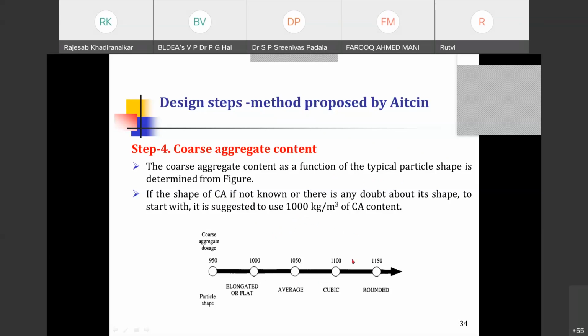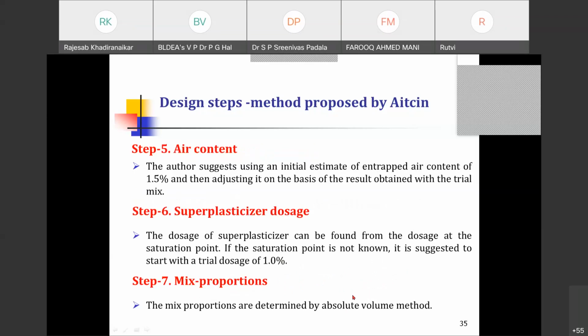If you have a clear-cut idea regarding the type of aggregate, then you can start with a range of 950 to 1150 for elongated and flaky. An average in this range, then for cubic shape you can go slightly higher, and for rounded still more. So based on the type of aggregate, you decide between 950 to 1150 kg per cubic meter. After that, the air content, and the authors normally suggest around 1.5%. But of course, it also depends on the superplasticizer that you are using.